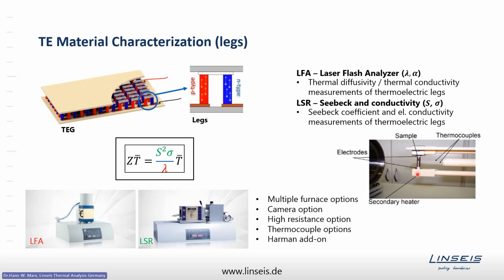This is how it looks in real life. So the thermoelectric material here is placed between the two holders, one containing a gradient heater, heating up the sample and creating a temperature gradient in it, and two probes measuring the temperature and the voltage drop. There are a couple of options available, like multiple furnace options, a camera which allows to measure the distance between these two probes with a very high accuracy. There are options to analyze thin films in such a device with a so-called high resistance option. There are different options for the type of thermocouples used to measure the temperature gradient. And there is a so-called Harman add-on, which allows the direct measurement of the figure of merit.